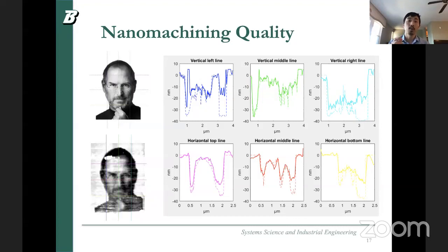Because of the tip wear, we cannot machine many 3D patterns with the same fidelity or quality, because the tip is going to gradually wear. Even though we add vibration in the X, Y, and Z directions, it will still cause tip wear. We cannot manufacture 20 or 30 patterns without fidelity degradation. So we're thinking about reducing the force when we're doing the nanomanufacturing, right?